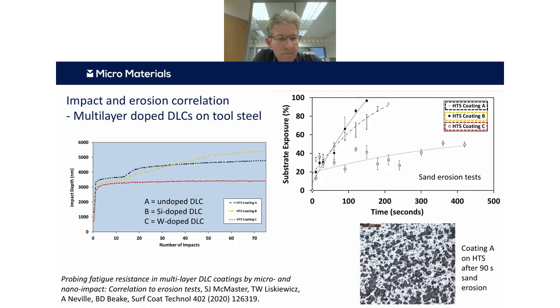So this is some work we've done more recently, in collaboration with Thomas, who's now at MMU, and Sam, who you've just heard from in the introduction. And here we were looking at whether we could use the test technique to correlate with sand erosion for diamond-like carbon coating systems that were deposited on a hardened tool steel substrate. So in this case, there are 3 different coating systems. They're all around 3 or 4 microns thick.